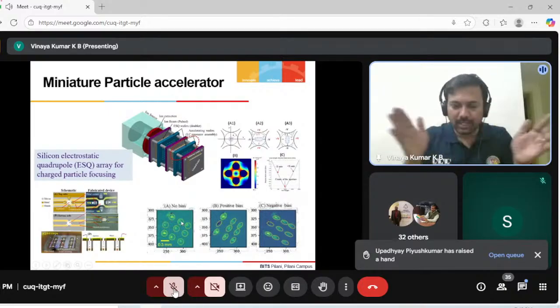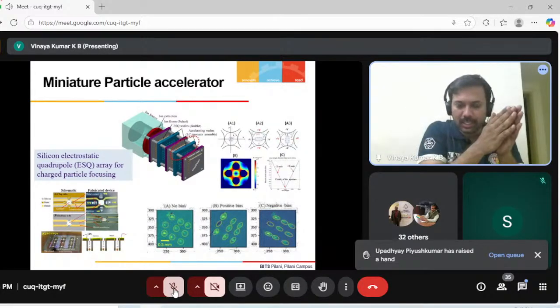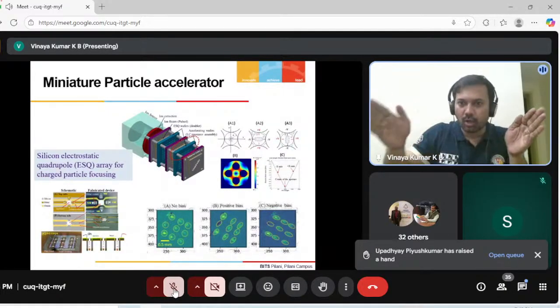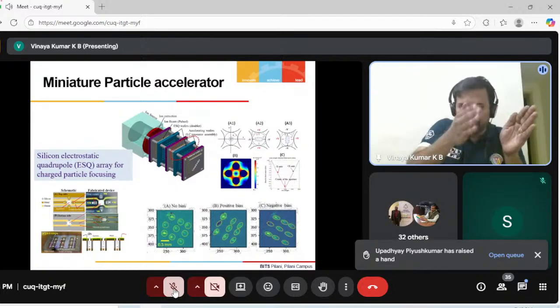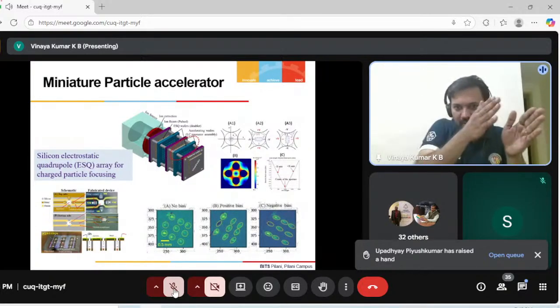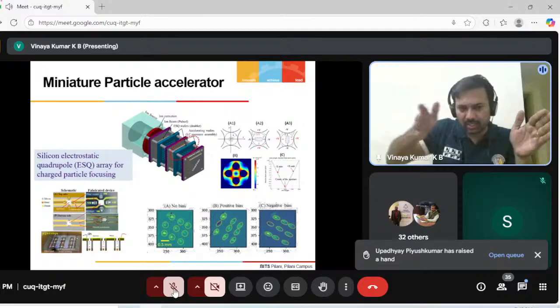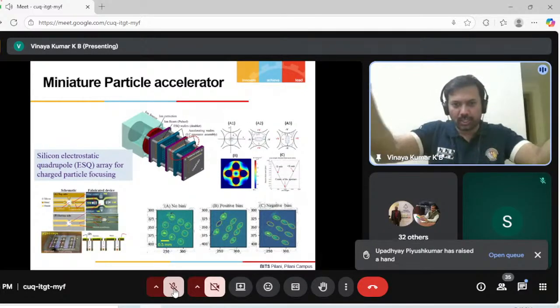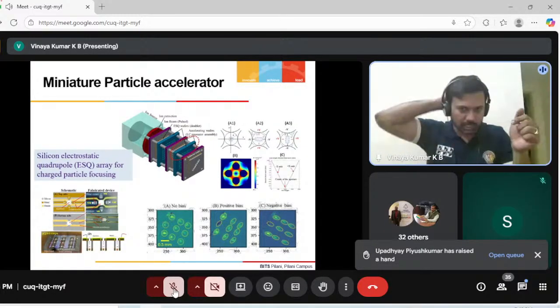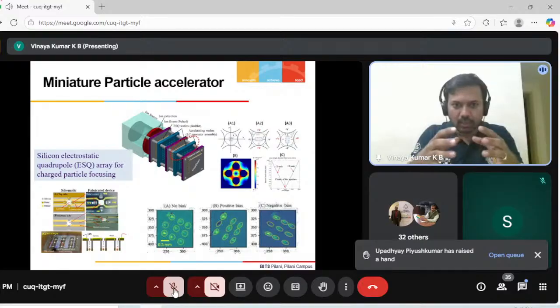So whenever in the accelerator the beam is moving for a very long distance, you're accelerating the beam in several stages. When you are accelerating the beam in several stages, you need to focus it also. Otherwise, the beam is going to diverge and you're going to lose a lot of beam energy. So these electrostatic quadrupoles are completely fabricated on silicon.